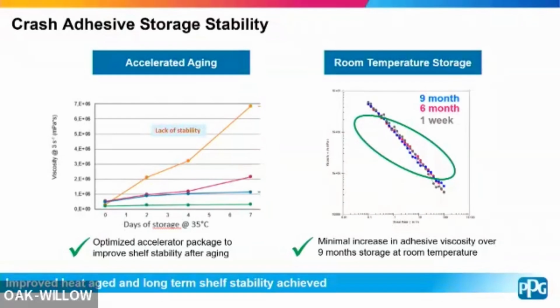Of course, you want to translate that to real life conditions, so that would be more of a room temperature storage. So we did measure, this is a viscosity versus shear rate curve, just showing performance at 1 week, at 6 months, and at 9-month room temperature storage of the material. You can see very similar behavior between all three of these time points, that really nice shear thinning behavior. You would want very minimal increase in adhesive viscosity over the course of that 9 months. So we were able to achieve both heat age as well as long-term shelf stability for this product.